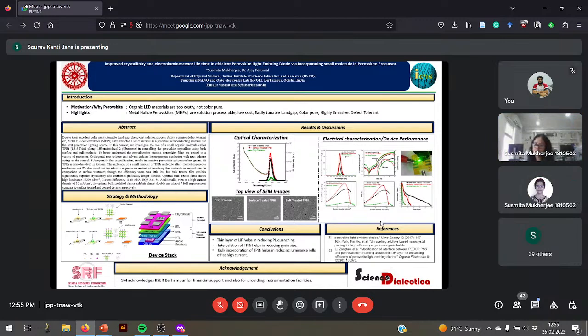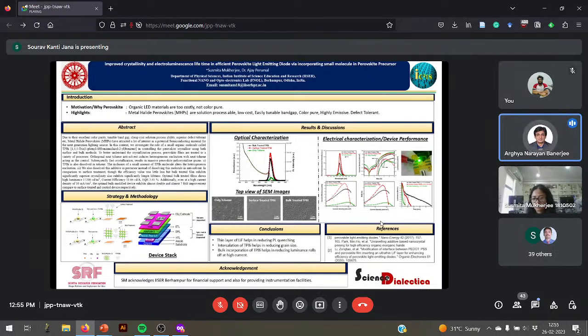So I have a question, Sushmita. You told that you are depositing the perovskite thin film by spin coating, right? Yes. And for the electrode packaging, you are doing the evaporation technique. Yes. So what is your film thickness? For the ITO and the glass, we commercially buy, so that thickness is roughly 200 nanometer. The PEDOT layer I spin coated, the blue color layer, is roughly 40 nanometer. In between, there is a thin LiF layer, 3 nanometer. The perovskite MAPbBr3, the green emission layer, is roughly 200 nanometer. The TPBi electron transport layer is 50 nanometer, and the cathode, the LiF and cathode combination, is 100 nanometer. So these numbers you chose through experiments, or you just followed some literature value?